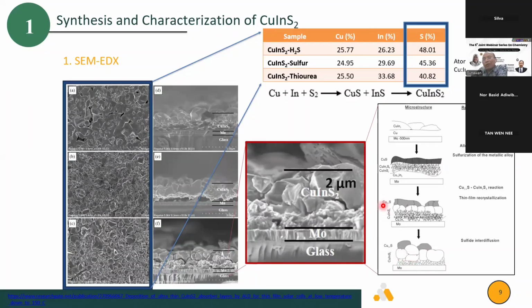So as I said before, besides the copper indium sulfide, it also forms copper sulfide, Cu(x)S, that should be removed from the copper indium sulfide so that it will not influence the performance of the copper indium sulfide. So we remove it by KCN, potassium cyanide, to remove the copper sulfide here.